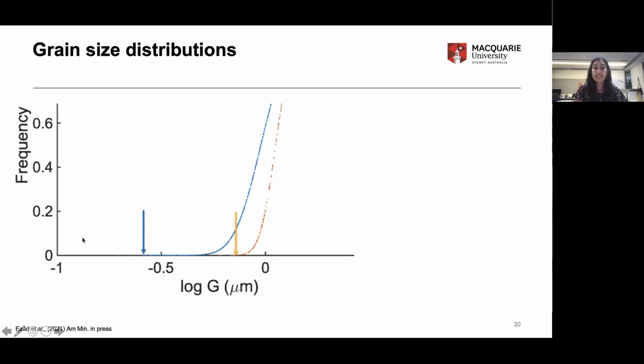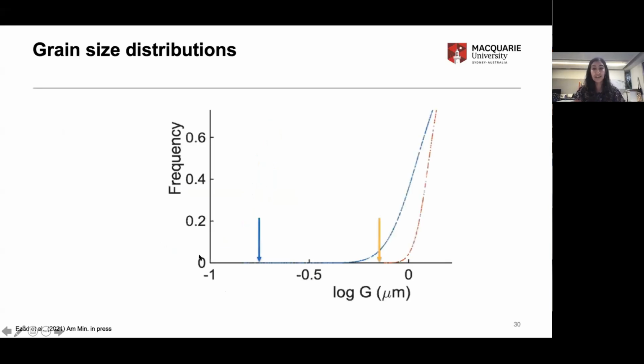But with the grayscale intensity values, it's a quantitative approach to doing this. And the story was the same over and over again. For every sample that I did, the tails of the distributions to smaller grain sizes were much, much greater in the automated approach compared to the manual approach.